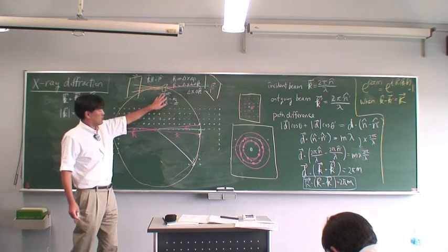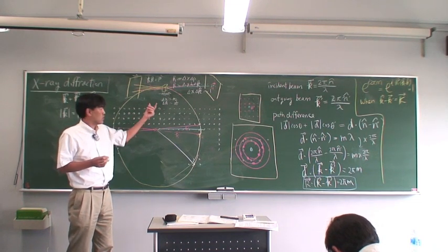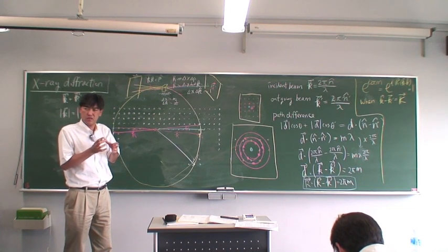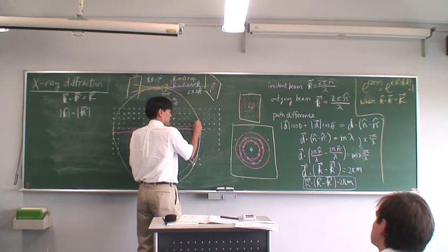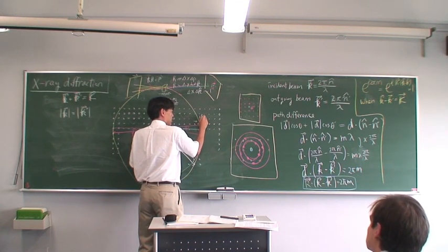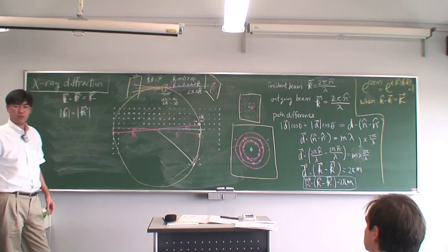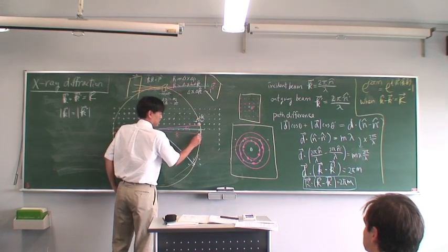In real life, when we perform X-ray diffraction, we probe a crystal of a certain size. So the size of this point is delta k. Because it's reciprocal lattice space, k space, it becomes big. And this way we get lots of overlaps.